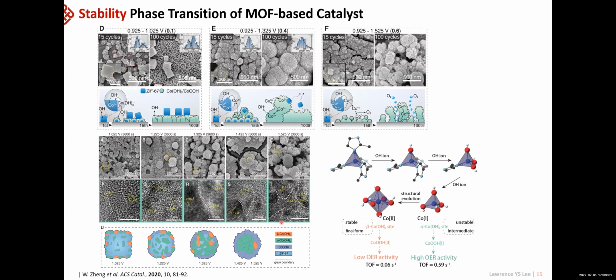So based on these spectroscopic and microscopic images, we believe that the initial MOF structure will change to either alpha species, alpha cobalt hydroxide, or they can actually be converted to the beta phase, and they have different activity for OER, but they are the ones that were actually converted to the active species of cobalt hydroxide.